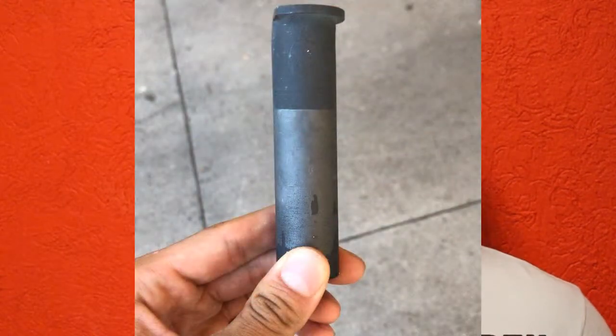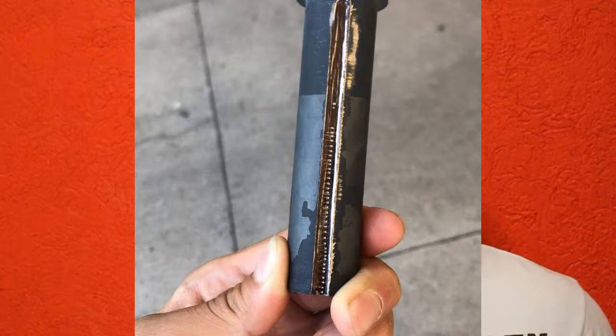After that, we took our material to the mill. In the mill, we made some cuts so we could take off the surrounding of our material, and we could apply some Rockwell tests directly to our material that had already been treated. After this, we did the Rockwell tests. It was every 1/16 of an inch for 2 inches. So we had 32 Rockwell tests, and then we plotted it in a graph. In one axis we had the Jominy test, and in the other axis we had the distance from the bottom part to the top part. So in this way we're going to see how the hardness of our material varies.